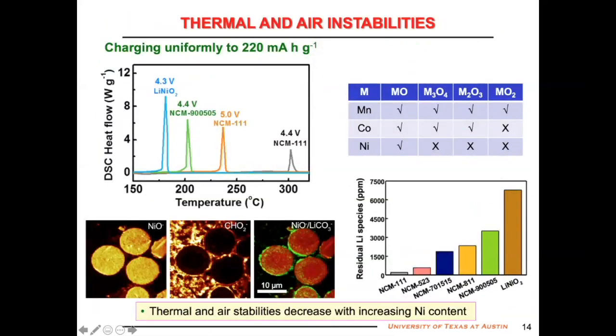Safety or thermal. To compare the thermal stability, we have to charge them to the same capacity, otherwise it will not be a good comparison. So this is after charging to 220 milliamp hour per gram. As you see here, when the nickel content increases, the thermal stability decreases. That is understandable. Manganese has all kinds of oxides, 2+, 3+, 4+ oxide. Cobalt has only 2+ and 3+ oxide, no 4+. Nickel has only 2+ oxide, not even Ni2O3. Therefore, nickel is much more unstable in contact with the electrolyte. So that's why the stability is decreased.